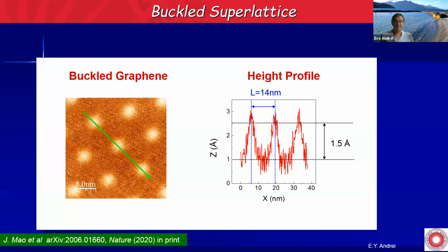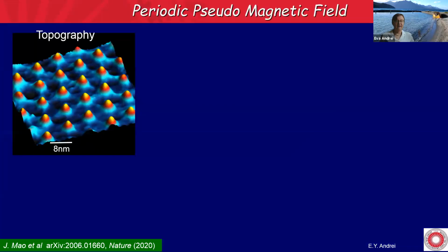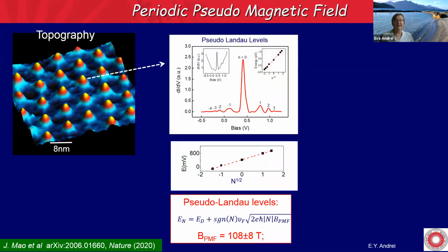And this gives us a periodic pseudomagnetic field, which actually oscillates up and down. And in the topography, here is what it looks like. These are the peaks, and here are the troughs. So if we take the dI/dV spectrum on one of these peaks, we get this beautiful pseudo-Landau level structure. Now if we fit the energy sequence as a function of the square root of the Landau level index, we can extract the pseudomagnetic field, which is about 108 Tesla. It's a huge pseudomagnetic field that comes from this compressive strain.